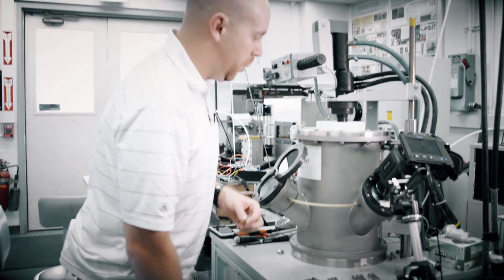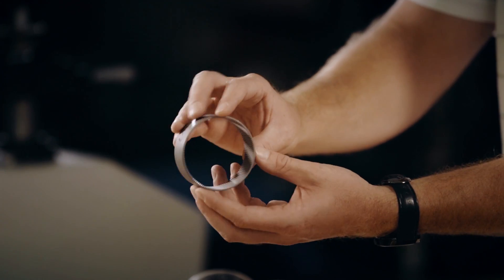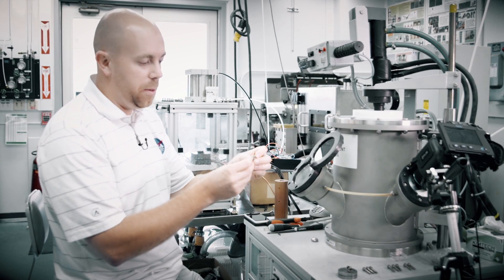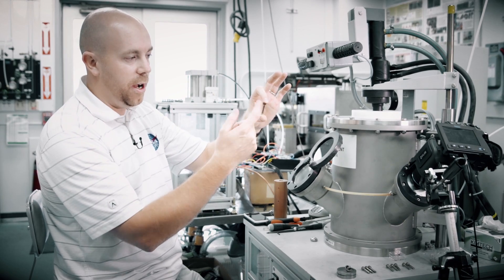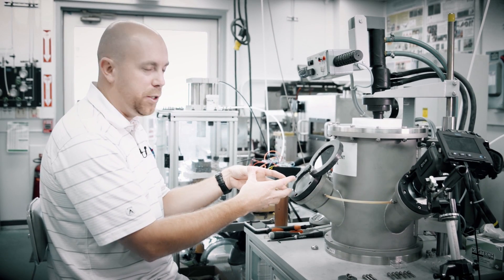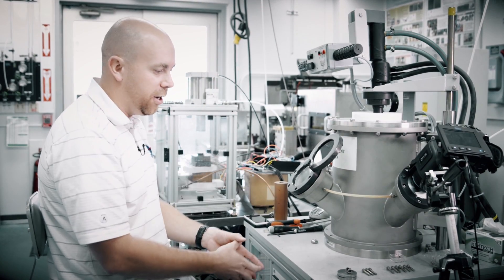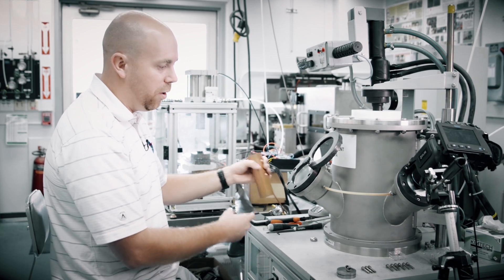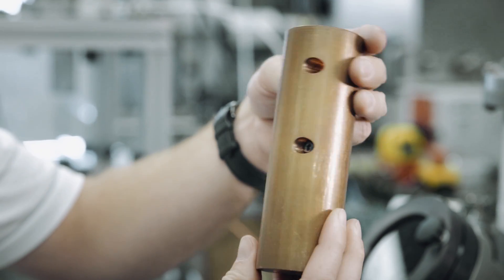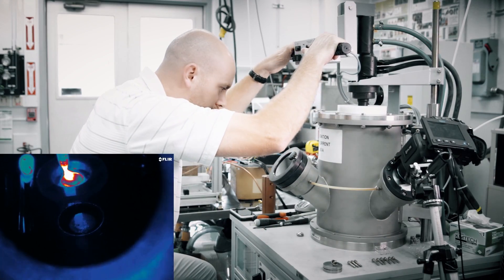One of the things we do with metallic glass here at JPL is cast metallic glass into gears and make all kinds of gear components. In this case we're going to make a pinion gear — a rod with gear teeth around it that fits inside a small robotics gearbox. We melt the metallic glass in a crucible, then push a foot pedal to apply suction pressure to the liquid, which sucks it into a mold below the hearth that has a gear mold inside it. So I'm going to melt the ingot and then suck it into a mold to form a gear — and there it goes.